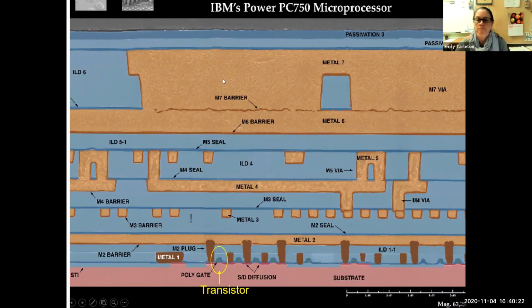So at one point, the gate was this big, and this was state-of-the-art technology, and the back-end interconnect was much bigger. So 248 at one point was the gate, then it moved back to these layers. Same with 193, it was the gate, it moved back, and now 193 is putting a lot of these layers, 248 up here, and then I-line, G-line. We still sell much more volume of the older technologies.